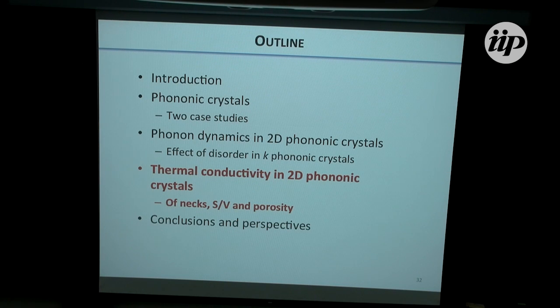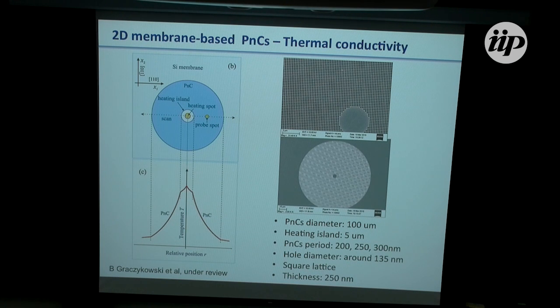So let us now go and see the thermal conductivity of the phononic crystal, but paying a little bit more attention to the surface to volume ratio, or what I think we are used to calling the porosity. For this structure, we decided to change the sample design a little bit, and to deposit a metal as a heater for our crystal. So this is where we put our laser. This is the metallic part here. And we measure scanning away from the heating spot. So typically, this is what we would get. This change of slope is because here we're in the metal part, and here we're in the phononic crystal part.